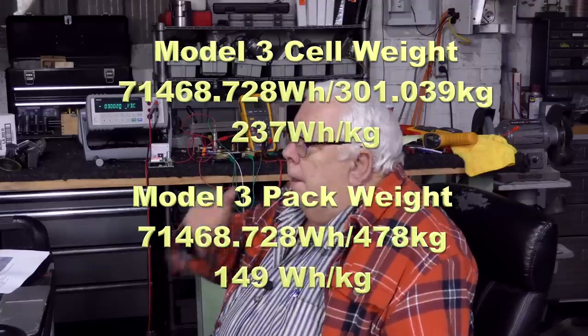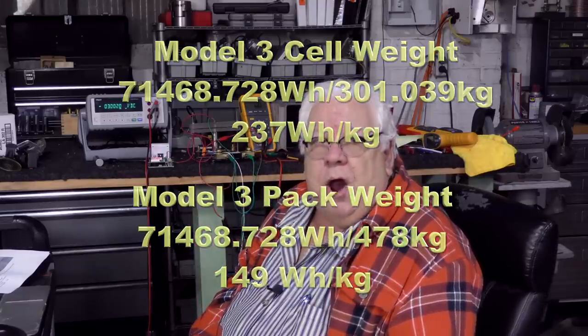Again, doing lab spec for advertising, they were undoubtedly doing that at 0.1C. It doesn't account for this much difference, but some. And we were attempting at 1.25 amps to do a 0.25C discharge, more representative of you going from fully charged to pretty much fully discharged at 70 miles an hour on a freeway. So a little more real-world thing. The time that we wound up with was 214 minutes, and that corresponds pretty much to about a 250-mile range at 70 miles an hour. And my experience with a car would be kind of dead nuts on that.